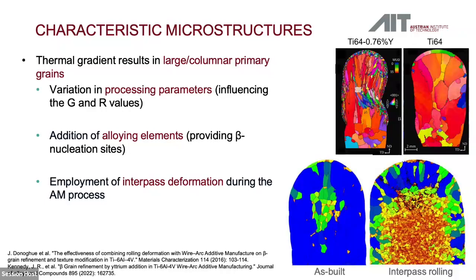Options to overcome these shortcomings are variations of the process parameters that can help you to reduce the grain size. Alloying element additions, that is exemplarily shown here. Yttrium, for example, can result in grain refinement. And the third option is interpass deformation, which can be rolling or peening, and is very effective in terms of grain refinement. But if you have to incorporate that into your process, it will also give you some limitations in terms of the complexity of the part that can be built.